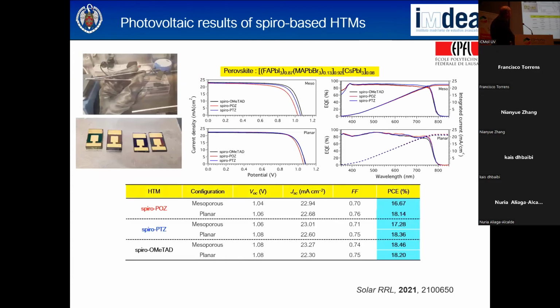And now we go to the photovoltaic device, and you can see that we prepared the mesoporous configuration and the planar configuration. Mesoporous was carried out at EPFL in Switzerland, and the planar was carried out in Madrid. You can see here that the efficiency is pretty much the same. If we go to planar, spiro is over 18 for the spiro-OMeTAD, similarly. So the electronic is pretty much the same. But look at this, here we start to see the difference.